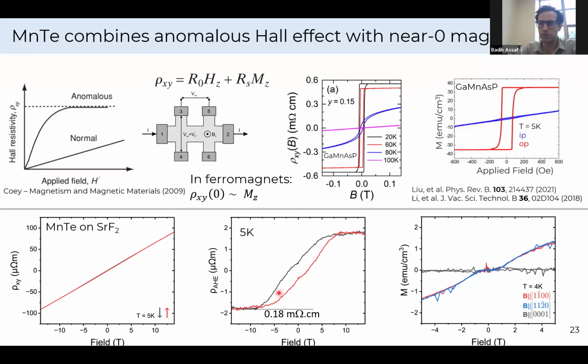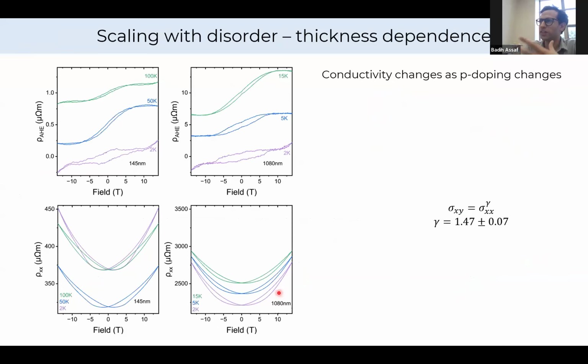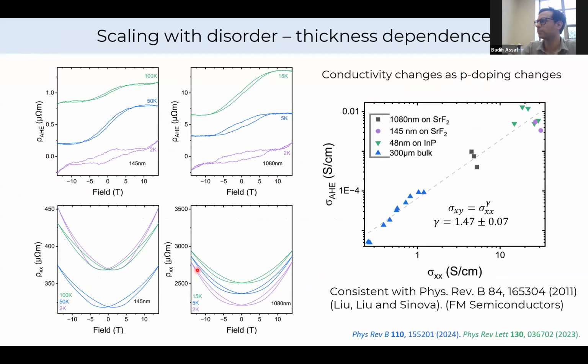We wanted to be sure that this is intrinsic, so we took this a step further. We did a thickness dependence. And it turns out when you change the thickness of manganese telluride, its longitudinal conductivity changes because its carrier density changes a little bit. And what that allowed us to do is to actually study the scaling of the anomalous Hall effect. So here I'm showing anomalous Hall resistivity, and longitudinal resistivity. But from these quantities, you can actually extract the conductivity, sigma xx and sigma xy, and you can plot the scaling relation between the two. That tells you something about the origin of this anomalous Hall effect.